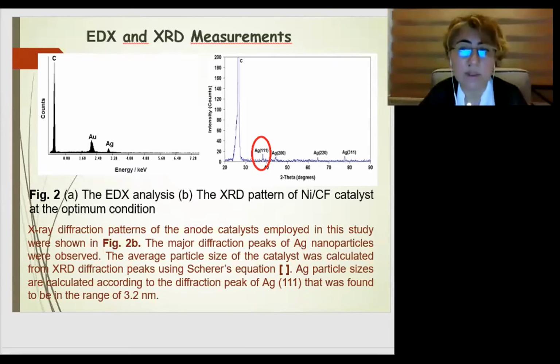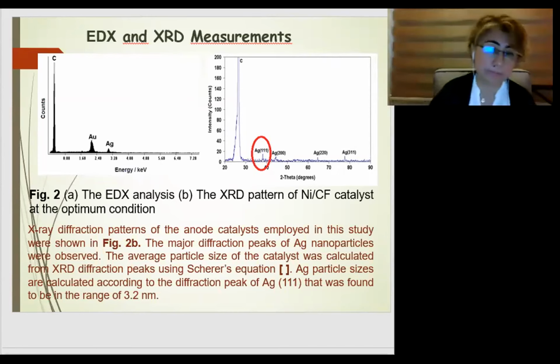The average particle size of the catalyst was calculated from the XRD diffraction peaks using the Scherrer equation. Silver particle size was calculated according to the diffraction peak of silver (111), which was found to be in the range of 3.2 nanometers. So the average particle size of the silver particles is 3.2 nanometers.